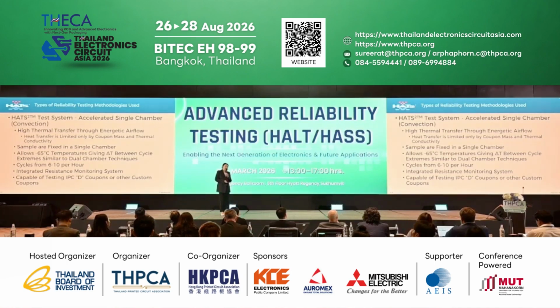It allows the airflow of the lowest testing condition to be -65. The high temperature can go as high as 265 degrees C. It can shorten the test cycles from typically, a traditional thermocycling test is 1 cycle per hour. With HATS testing, it can be shortened to 6 to 10 cycles per hour.